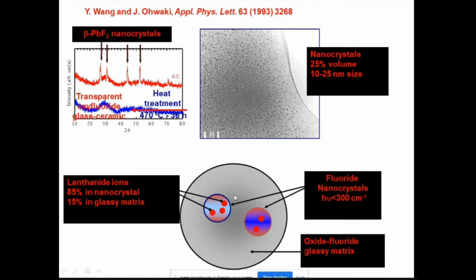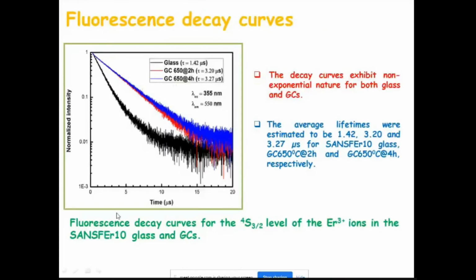Inside a glass, I am able to nucleate crystallinity, so that the optical properties will change. And now, just you see, I'm giving a decay curve. It is very important, because luminescence materials mean how fast the light emits and how fast it changes from one color to another color. All depends upon the decay. Once the atom gets to an excited state, it will come back. While coming back, it is called a decay, disintegration. And this decay time is very, very important for any display devices.